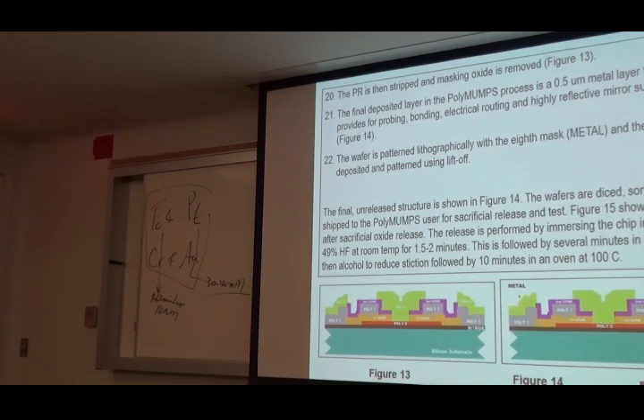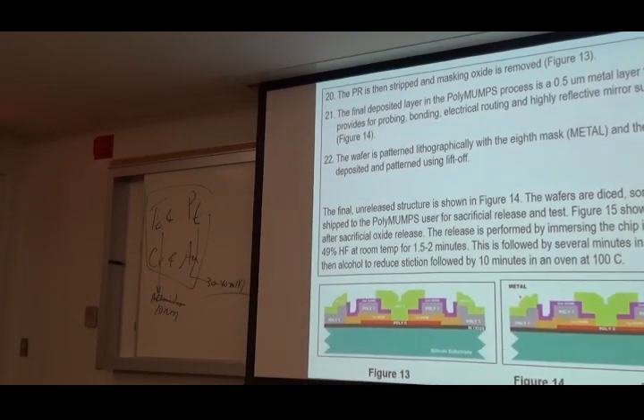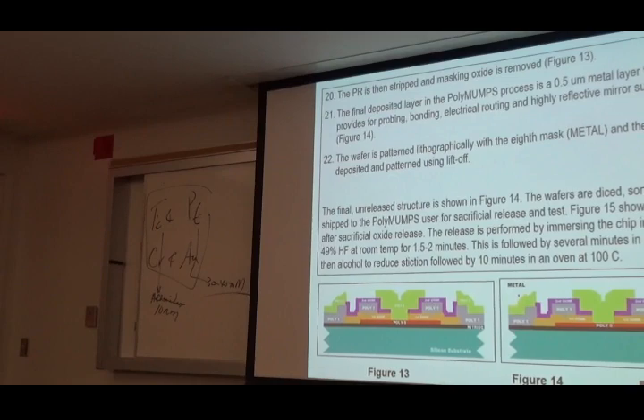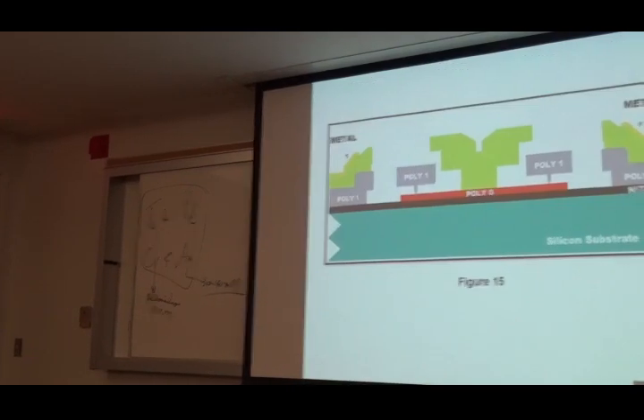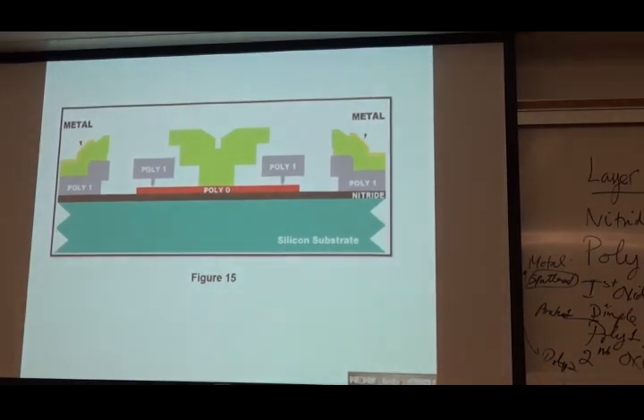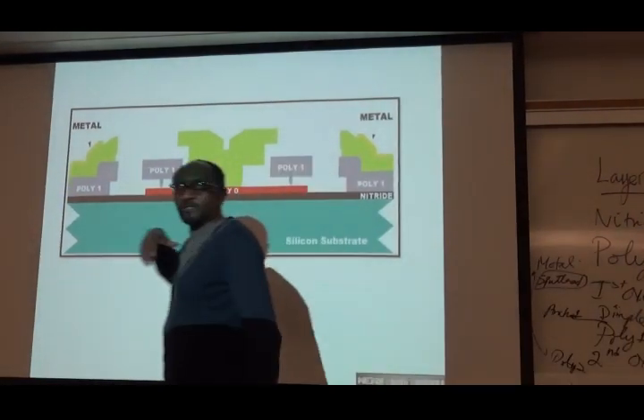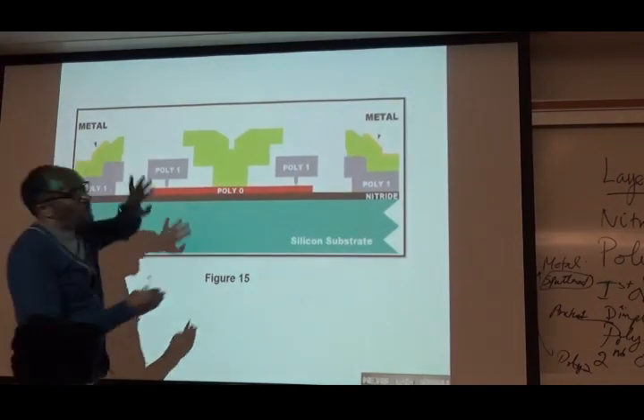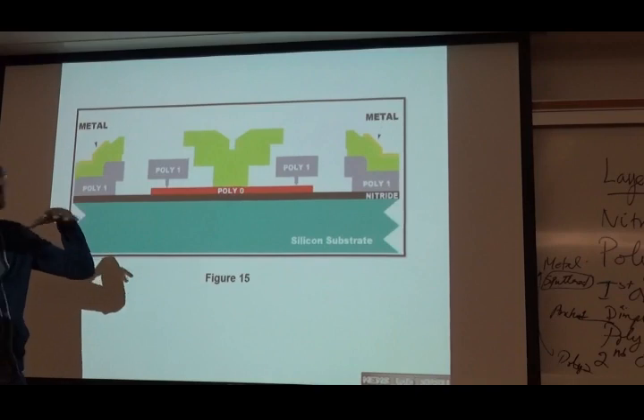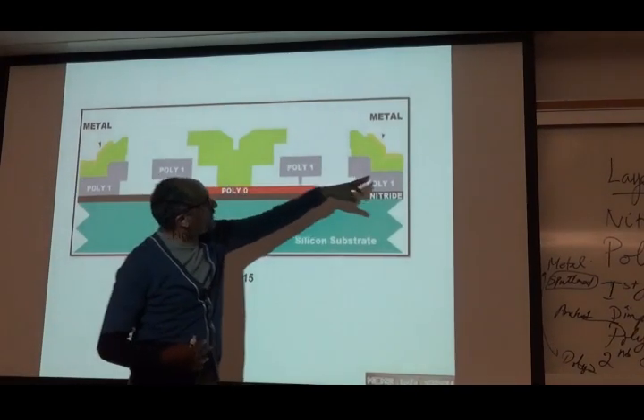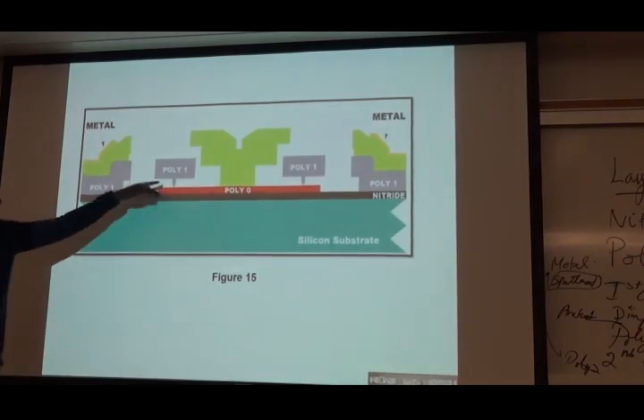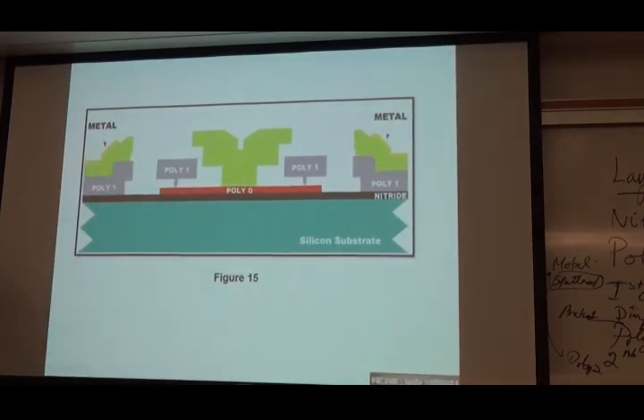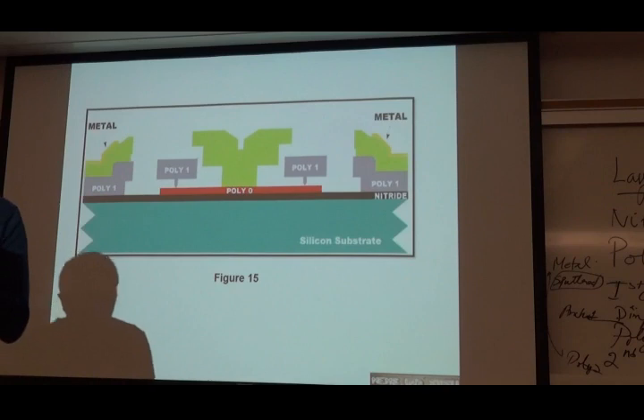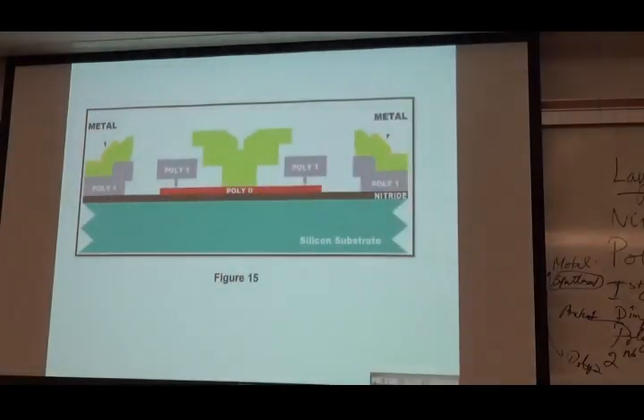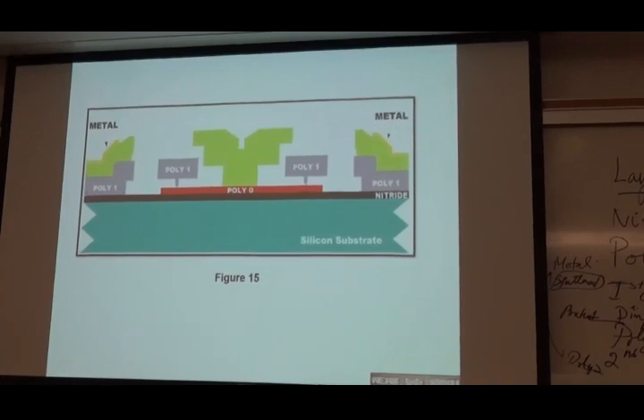At the end you have your metal, so the only thing remaining is getting rid of the oxide. Oxide 2 gets washed away, oxide 1 gets washed away. Then, voila, you get this cartoon, very similar to homework number 2. You have an anchor on that side, which is supporting the beams, and the proof mass, and another anchor here. Poly 1 has its dimple and all that. So the process in general looks like this: 3 polysilicon layers, 2 oxide layers, and 1 metal layer. All right, congratulations for surviving.